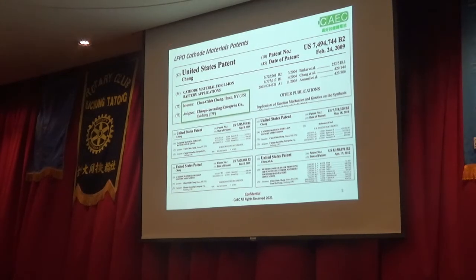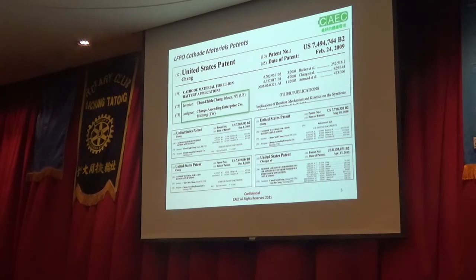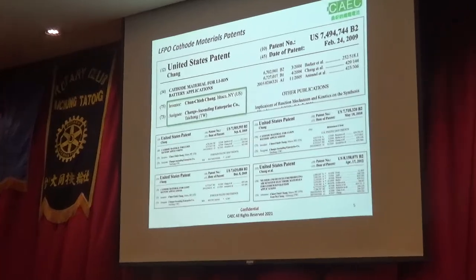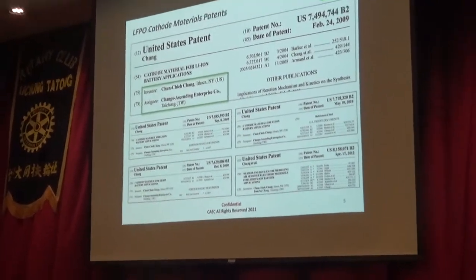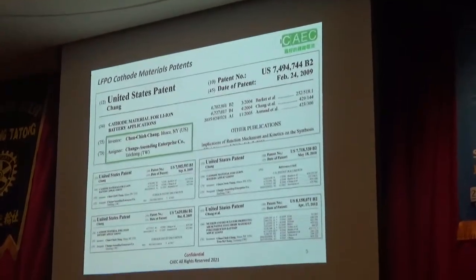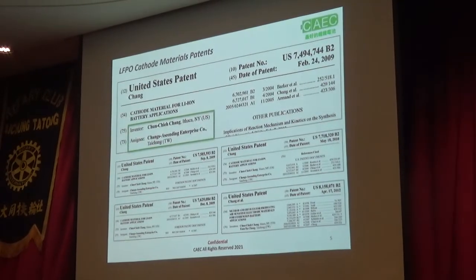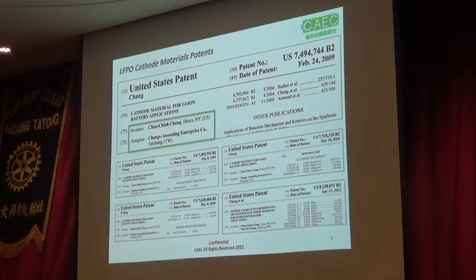There was a story. The major breakthrough of this material is that we synthesize this material in air atmosphere, not inert atmosphere. Well, it's a little bit of reverse engineering, how to mass produce this material in normal atmosphere. And then you have to change the structure, and you have to change the electrical conductivity of the material, etc. So at that time, I tried to dissolve some so-called aliovalent cations into the structure that enhance the electrical conductivity of the material. And that enables the material to be successfully synthesized under air atmosphere. That means it can be mass-produced. So once the material is available, then you can talk about applications, right? Otherwise, there is no way for the market or the applications to become popular.